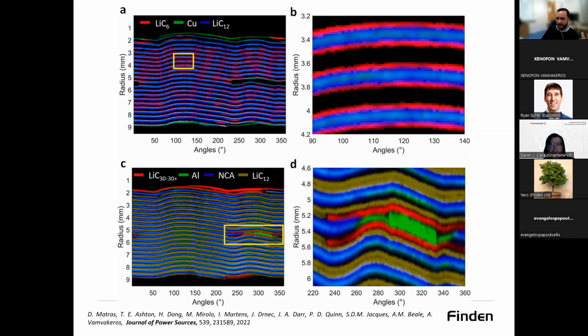Because these are images, we can, of course, virtually unroll the cell if we wish, because we're just going from Cartesian to polar coordinates. And we can, again, notice various things. So if you remember the previous static experiment, here we can again see green is the copper current collector, blue is the lithium carbon 12, red is lithium carbon 6. RGB is probably not the best way, but anyway. Again, we verify that it forms at the surface first, as expected, of course.